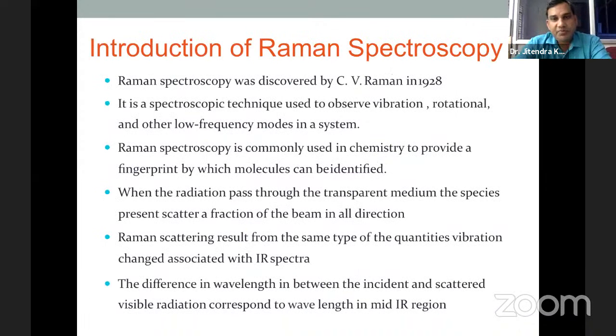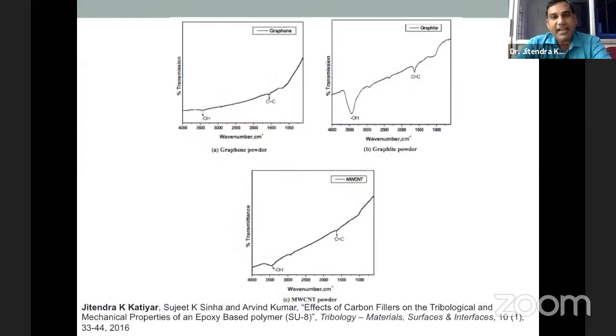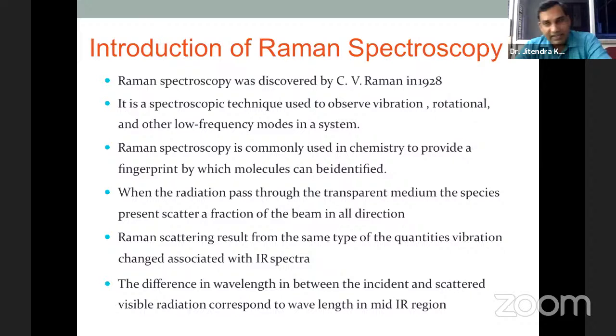So further we move to another technique, Raman spectroscopy, because in FTIR, infrared falls over the surface. So what happens, these infrared rays are absorbed by the atoms. So due to the absorption by atoms, sometimes if your coating is something you don't know much about, that is unknown, then don't go for FTIR, because sometimes it will not give you the correct result. Because the infrared is absorbed by the atoms, and sometimes it will not give you the correct result.